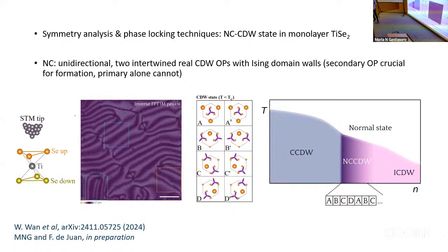And the second one is that the mechanism proposed for Cooper pairing in that case was some phase fluctuations of this incommensurate charge density wave. And it turns out that when you extract all the information, these are two intertwined real CDWs. So there is no phase degree of freedom. So now, I'm not sure how, or whether, this type of state would actually give rise to pairing. And then what we also find is that there are two order parameters. One of them is the driver, the primary, the other one is the secondary. And the secondary seems to be crucial. If it is crucial, what its role is for pairing is not clear.